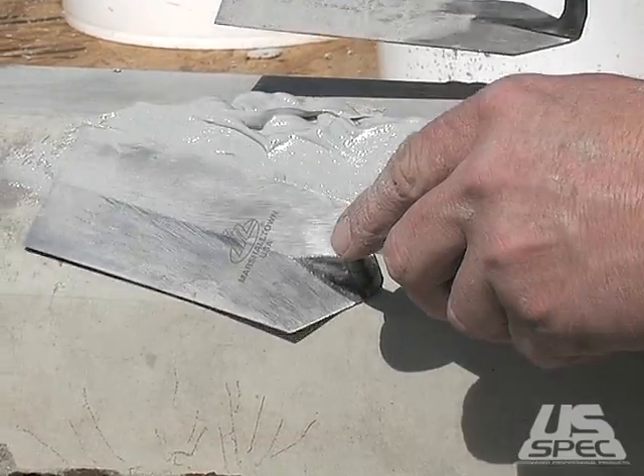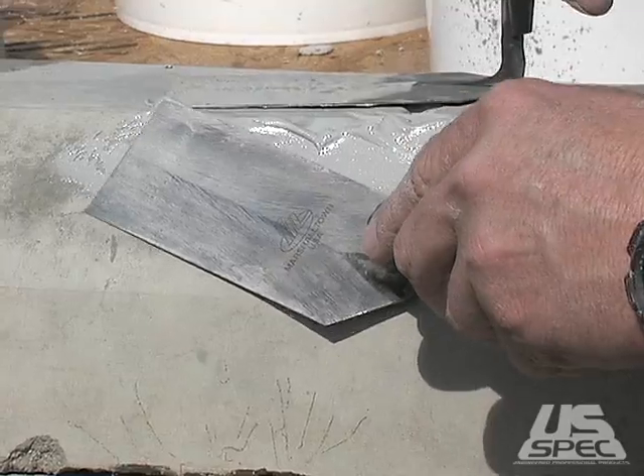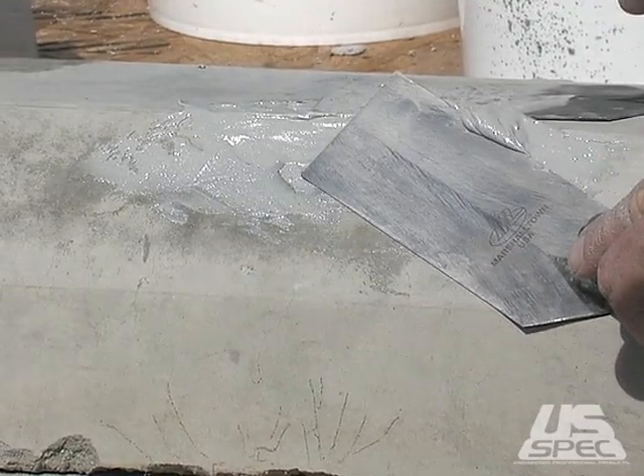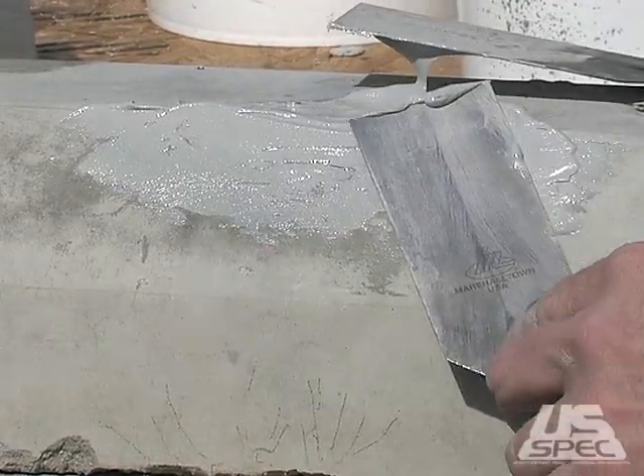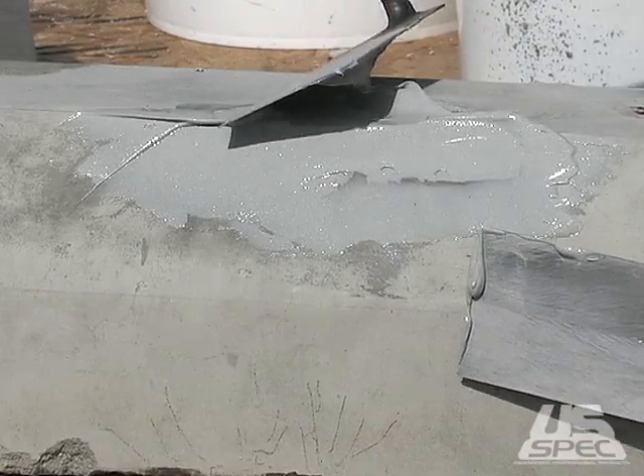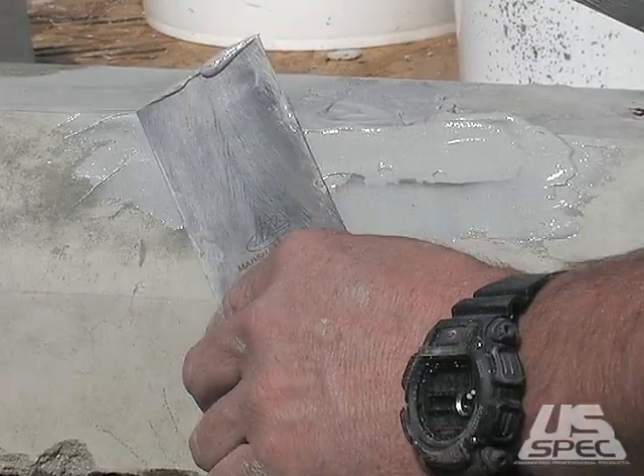US Spec Wonder Bond has a gel time of approximately 8 minutes and achieves 8,000 psi compressive strength in 7 days. The cure time for US Spec Wonder Bond is 2 hours at 75 degrees Fahrenheit.